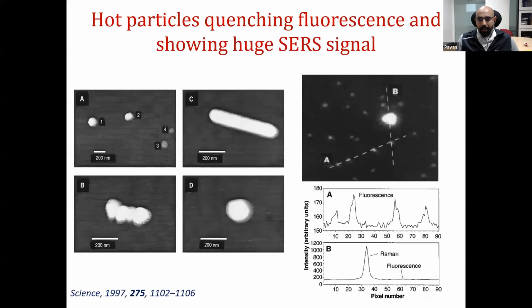Parallel to this kind of report was this very famous Science paper, where people reported hot particles quenching the fluorescence and showing huge surface enhanced Raman scattering. This is from Shuming's work, where they took AFM images of individual nanoparticles, and if you perform surface enhanced Raman scattering across, let's say, A and B, the A generally shows very high, large fluorescence spectra, whereas in B you can see that the Raman scattering signature is much more enhanced compared with fluorescence.